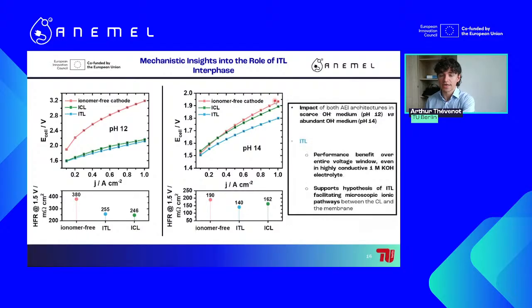And then regarding the ITL this time, we also see a performance benefit over the entire voltage window, even with a highly conductive electrolyte. And this supports the hypothesis of the ionomer top layer facilitating microscopic ionic pathways between the catalyst layer and the membrane.